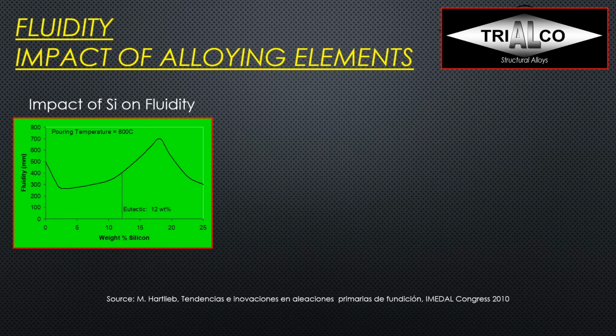Now let's talk about fluidity. So what is the impact of each alloying element? Well, let's first look at silicon, because it's the most common alloy family, of course, the 300 series with aluminum and silicon and something else. If I had just pure aluminum, my fluidity would actually be really good. My properties wouldn't be that great, but my fluidity would be just fine. If I add silicon, my fluidity first goes down until I reach maybe 3-4%. That's when it gets the worst, and from there on, it gets better.